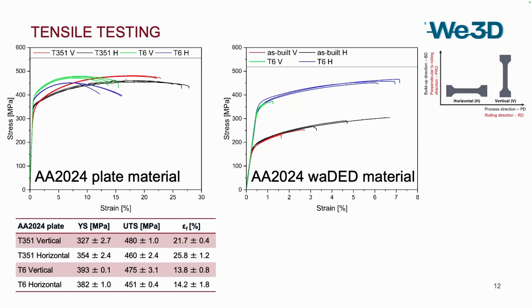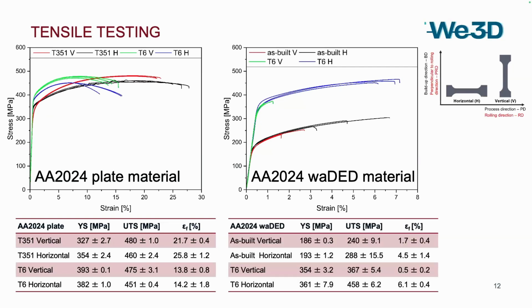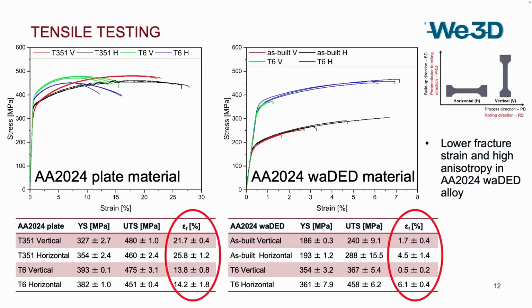On the right side, we have the wire arc DED material with the two conditions, as-built and T6. For the orientations, again, vertical and horizontal, we can see that the strength in the as-built condition is quite low, but this can be improved to a similar level, let's say, in the T6 condition, but we have also a high level of anisotropy. And furthermore, we have to mention that here the fracture strain is on a different level, quite low, 0.5% in the vertical T6 sample and 6% in the horizontal one. So different level of fracture strain, but this is similar to other works on 2024 wire arc DED material.